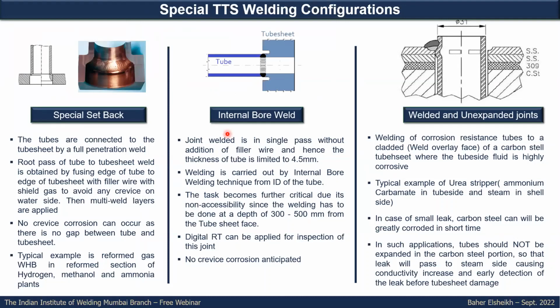Those are some of the special TTS welding configurations we can see in the industry. They are not listed in ASME, but they are used in many applications. This one is a special setback weld. We can see it normally in the welds of waste heat boilers in the reformer section of ammonia, methanol, and hydrogen plants, where there is a small lip in the tube sheet from the shell side. And the tube also has a lip like this, like a step. While welding, it will be fused together. So you will totally fuse this part, and you will not have any space or clearance where you can have a chance for crevice corrosion. And this is highly recommended for this service because the temperature here is very high.